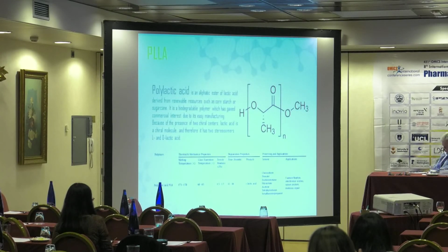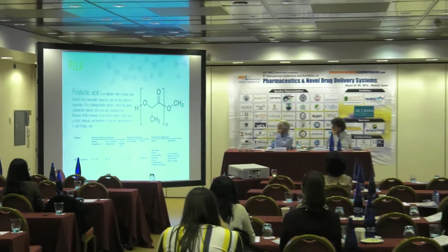Also, in one of the systems that I'm going to present here, we use PLLA. In this part, I only want to say that polylactic acid has a higher degradation time, as you can see there, from 12 to 18 months. The strategy that we try to use is to get copolymers between polylactic acid and polyethylene glycol in order to get a better degradation time in our systems, and also because of the requirements that we must take into account when we are talking about intravenous administration.